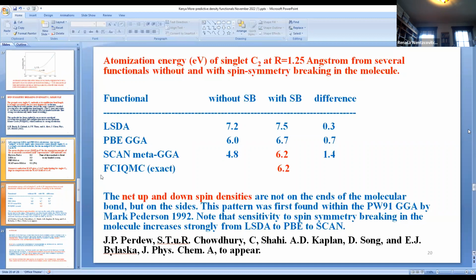When you go to the PBE GGA, the atomization energy without symmetry breaking is 6.0, and with symmetry breaking it's 6.7 - a difference of 0.7. But with the SCAN meta-GGA, there's a big difference between the symmetry unbroken and symmetry broken atomization energy. It changes from 4.8 to 6.2, a 1.4 electron volt difference.